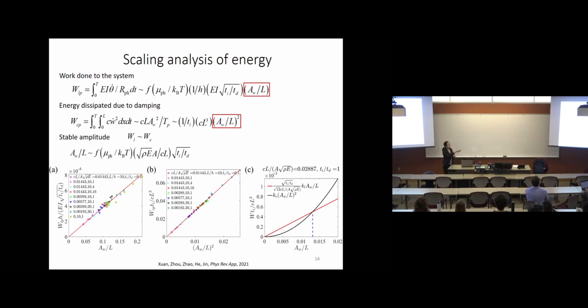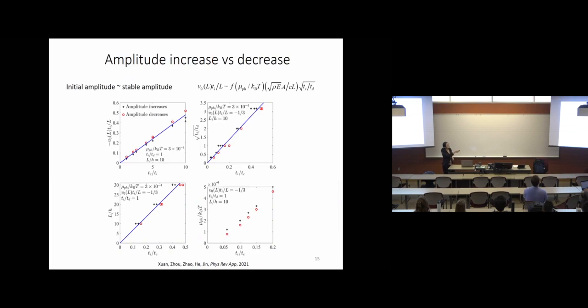So next, we do a scaling analysis to try to understand the energy. We found that the positive work done to the system is proportional to the amplitude, but the energy dissipated in the system is proportional to the amplitude squared. Therefore, by equating these two energies, that can give us the stable amplitude. Then by comparing the initial amplitude with the stable amplitude, we can determine a phase diagram which governs the amplitude increase region and the amplitude decrease region with respect to all the dimensionless numbers in the system.